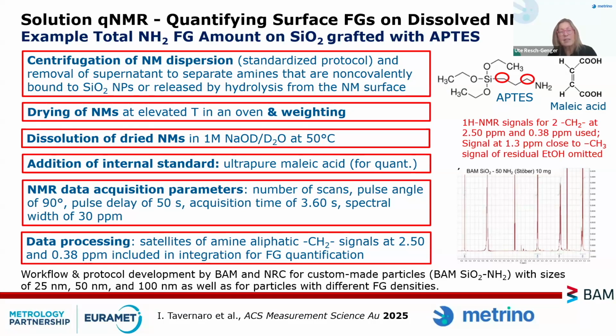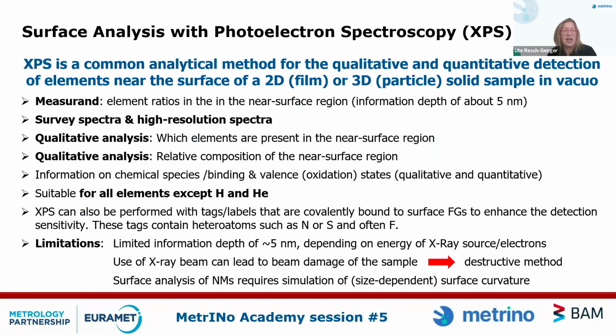We skipped the signal at 1.3 because particles were dispersed in ethanol before. So we wanted to make sure that we don't have interferences from ethanol. And we set up this protocol for 25, 50, and 100 nanometer sized particles because sure, particle size can, for instance, be relevant for centrifugation. So which speed is needed, such things. And this was refined with the aid of a comparison with another group because we really wanted to make sure that everything works out and that sources of uncertainty have been properly considered.